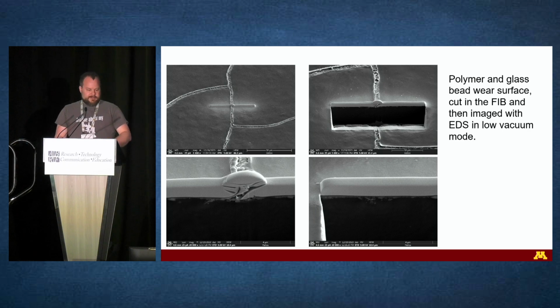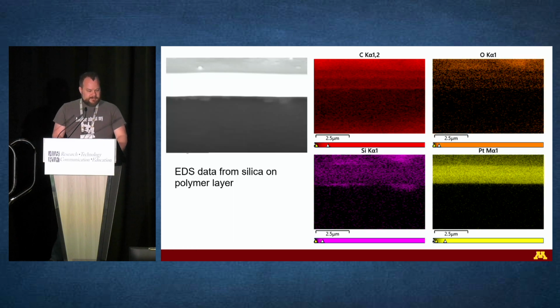So I put it into my FIB, I put down a protective cap of platinum, sliced it open, but my FIB doesn't have EDS. So I just took some pictures in backscatter, and we can see the bright layer beneath the platinum cap there above the darker polymer, which I thought pretty much proved it was glass, but they insisted I take it and put it in the other SEM and do the EDS on it. And you can actually see these little parts there in the silicon map show where the glass is. Those 2 bits there line up with the 2 bits in the backscatter image, therefore proving that it really was glass on top of the polymer.